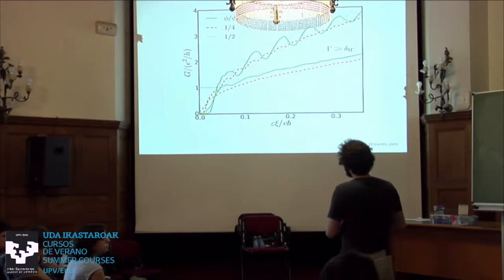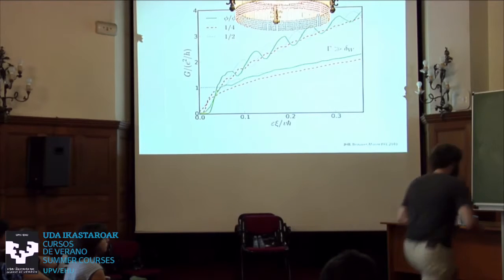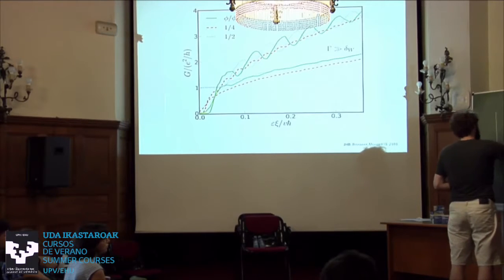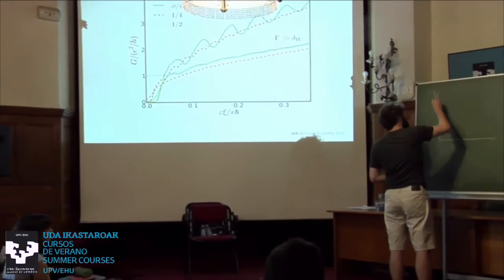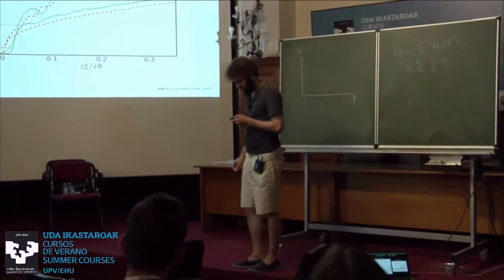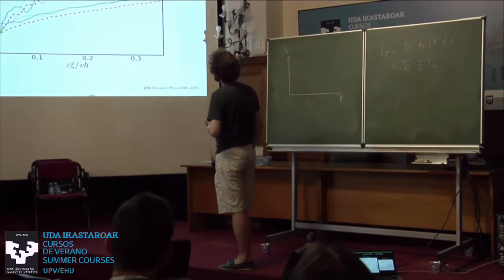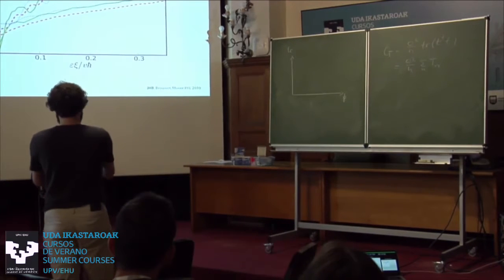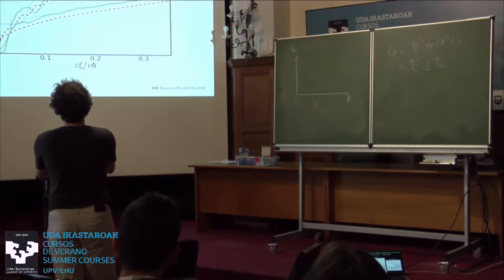And what you should look for is that, if I imagine that I fix my chemical potential here, let's say, I have only 3 curves, but just from these 3 curves, I know how something like conductance as a function of flux is going to look like. So let's say I'm here, where the green curve has a peak.